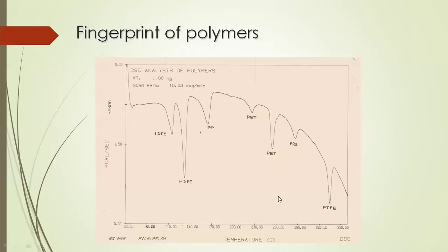Do a TGA. Suppose you get an unknown polymer. How do you identify it? Do a TGA and find out the degradation temperature. Then do a DSC 20 to 30 degrees below the degradation temperature and see the melting temperature, and you find out which polymer it is. This is how powerful the DSC and TGA combination is.